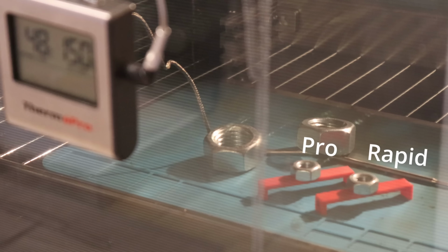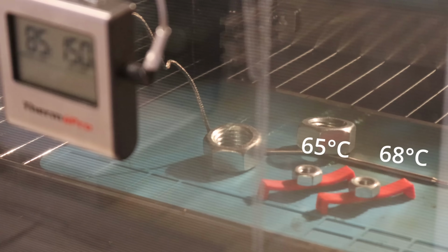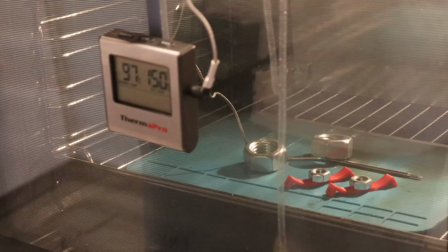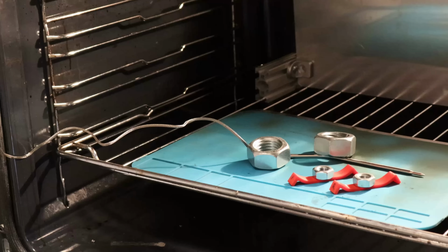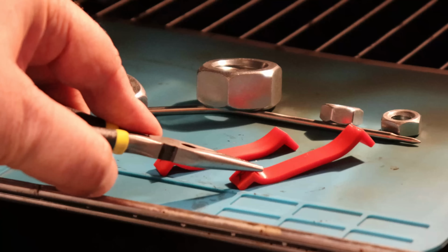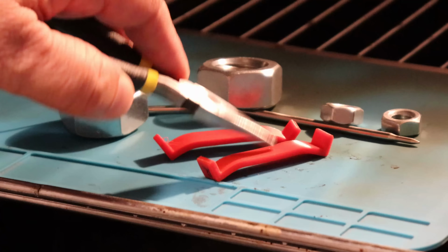Temperature test in the oven, M10 nut as a small load. And I started with deformation on 65 and 68 degrees Celsius. I stopped the experiment on 97 approximately, and of course they are very soft at this temperature, but think twice before you start drying on 70 plus minus 5 degrees Celsius as suggested.